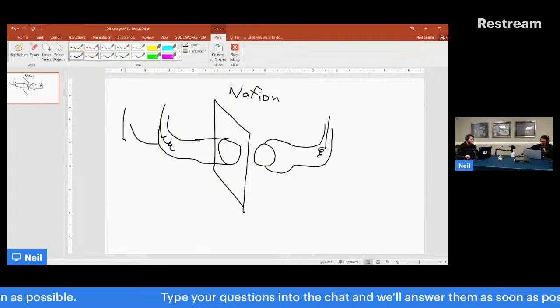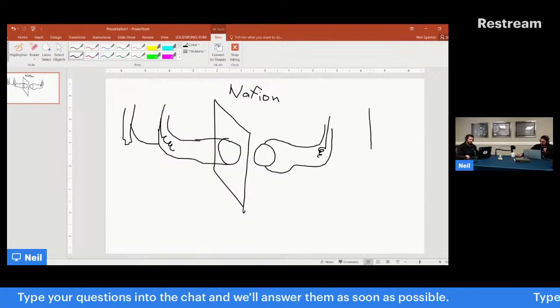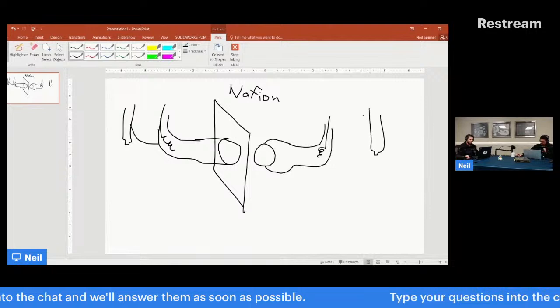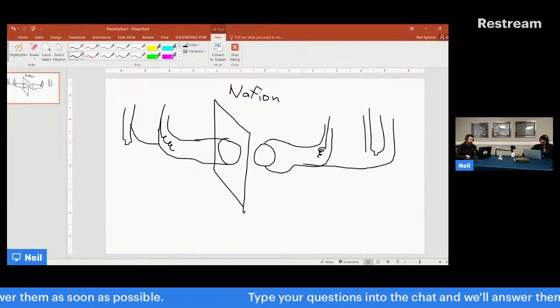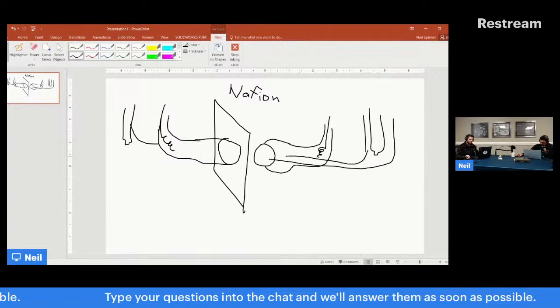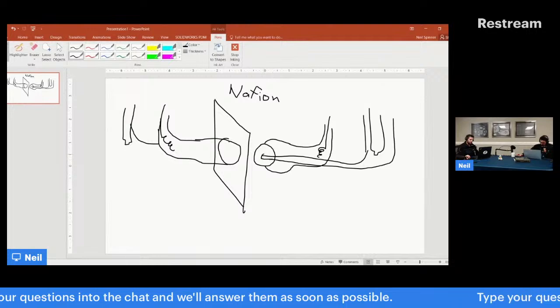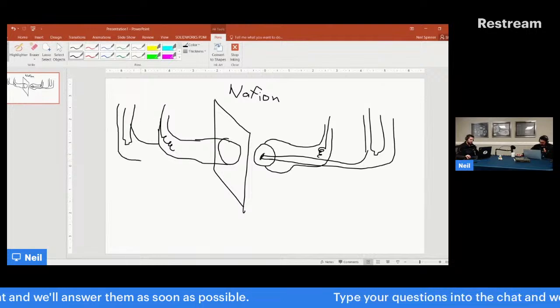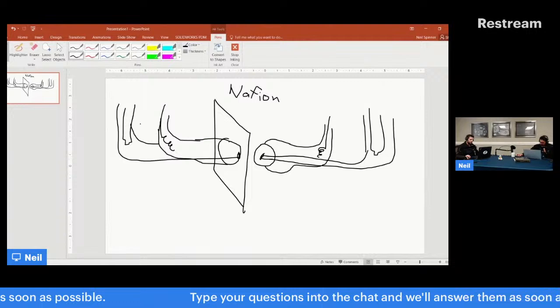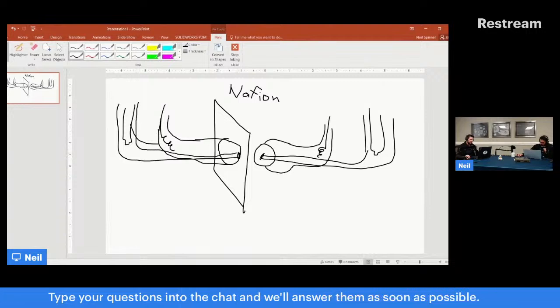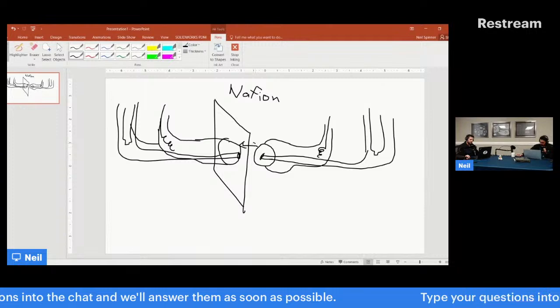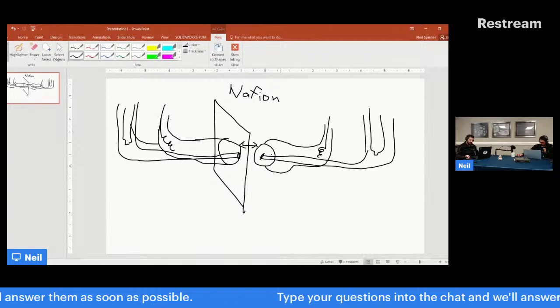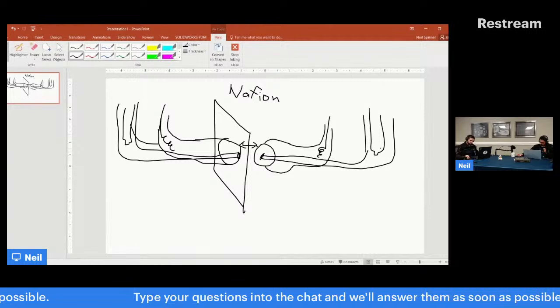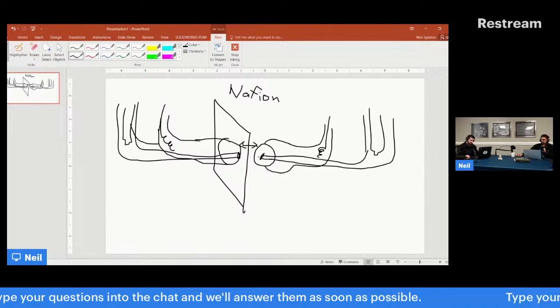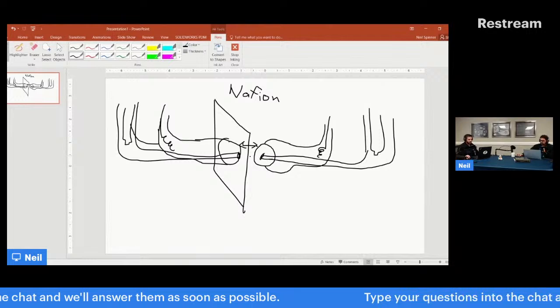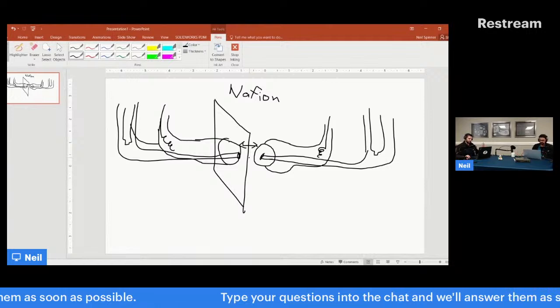So you have two reference electrodes on either side as well. This is the key to it. Basically, you have two reference electrodes with a Luggin capillary. This directs the measurement as close to the membrane as possible. So what you effectively have is a distance between these two reference electrodes where you're measuring. You're getting a potential measurement across this, and then effectively you do a 4-point measurement.